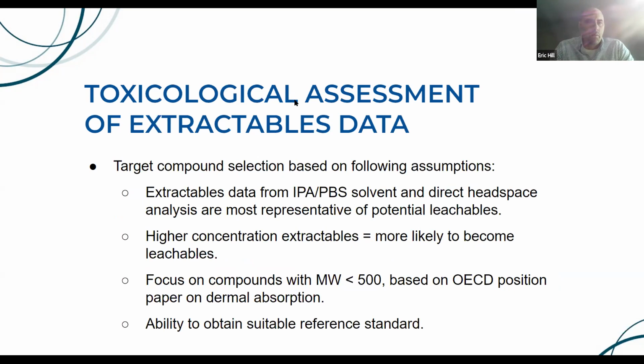And so from there, we generated our final target compound list based on the following assumptions. First of all, extractables data from the IPA and PBS solvent and the direct headspace analysis were the most representative of worst case potential leachables. Also, looking at the concentration profiles of our extractables compounds, higher concentration extractables obviously are more likely to become leachables.